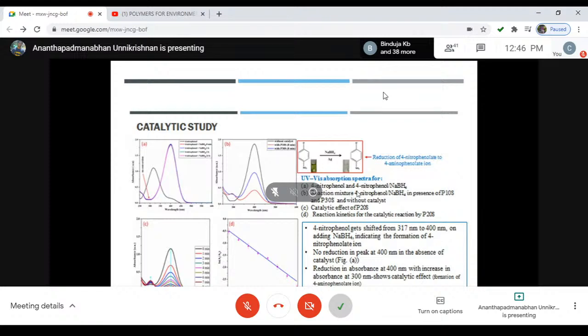So 4-nitrophenol reduction is shown here. The nitrophenol is slowly getting converted to the amino group, and the amino group generation is clearly shown by the absorption. This peak slowly goes up. The nitro group reduction is indicated by the reduction in this area. Meaning, what I'm conveying is that this UV visible strategy is an ideal strategy to follow the execution of a reduction reaction. You can observe the vanishing of some specific peaks and the appearance of other specific peaks. This is a fundamental reaction: nitro group getting reduced to amino group.